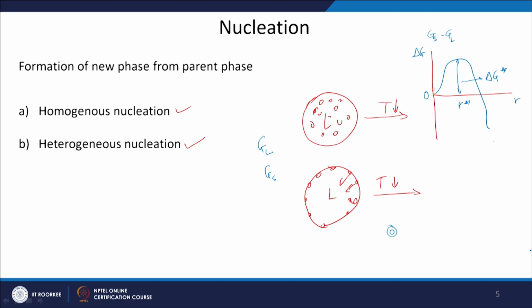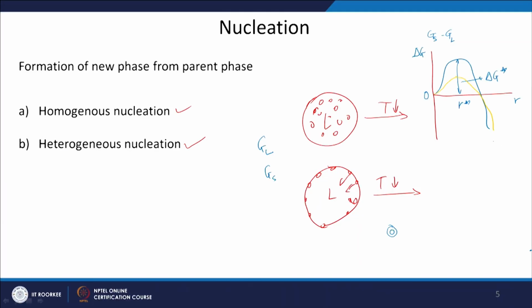Now, how will homogeneous and heterogeneous nucleation come into the picture in this? Suppose this is a curve for homogeneous nucleation, then for the heterogeneous nucleation, the curve will look something like this. That means R star remains the same, but my activation barrier has come down. So, when I provide a heterogeneous nucleation site, what I am trying to do is bring the activation barrier down. I now require a small driving force for changing from one phase to another phase, and that is why heterogeneous nucleation is the dominant nucleation mechanism when you have phase transformation.